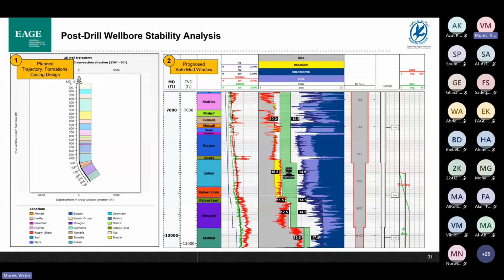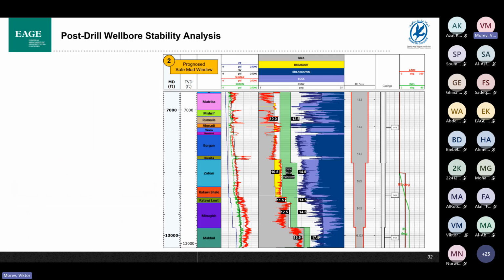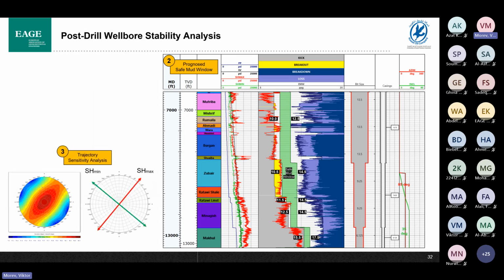Here it's worthwhile to mention that mud weight is not the only solution for solving all the wellbore stability issues. We have another tool, which is the trajectory. If we understand that the safe mud window is too narrow and risky for drilling some intervals, we check all possible trajectories with respect to the in situ stresses, because a change of trajectory often significantly increases the safe mud window for some problematic formations. So in case I have a very narrow window, I can play with the trajectory and understand what deviation azimuth would be the most preferable for this formation.